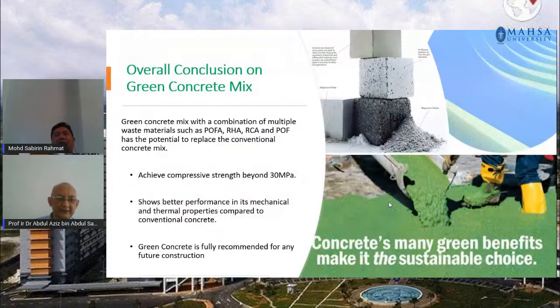So again, finally, this is the last slide, the overall conclusion on the green concrete mix. So from the green concrete mix, by adding palm oil fuel ash, rice-husk ash, recycled concrete aggregate, and palm oil fiber, it has the potential to replace the conventional concrete mix, okay, because firstly, it has achieved the compressive strength beyond 30 megapascal. Secondly, it shows better performance in its mechanical and thermal properties compared to conventional concrete. And finally, what I can recommend is that green concrete is fully recommended for any future construction in the Malaysian context. So with that, I end my talk today.